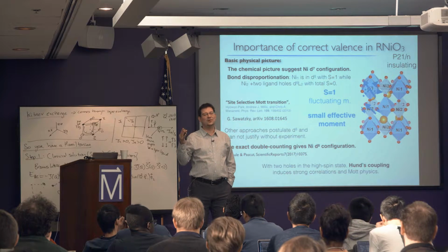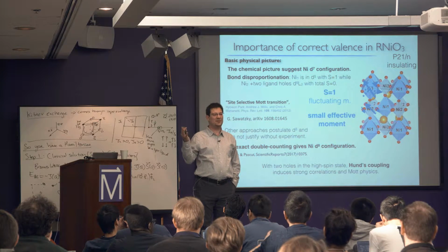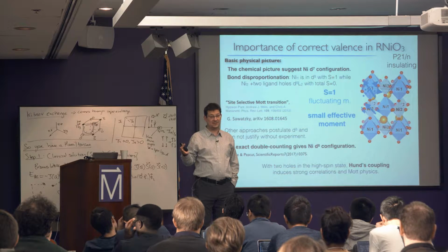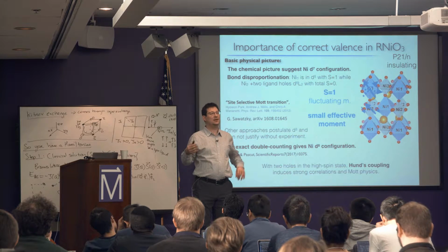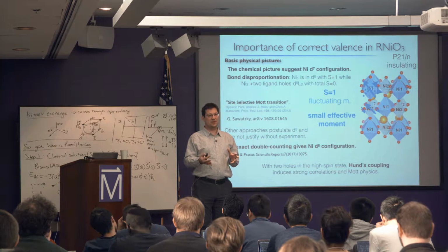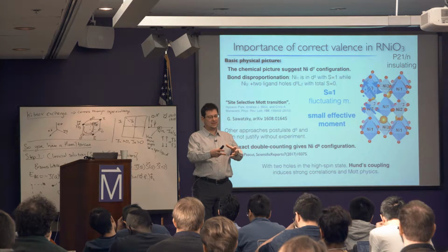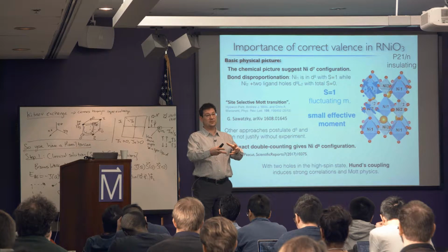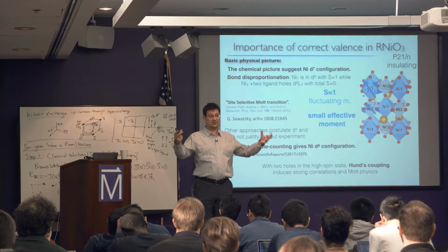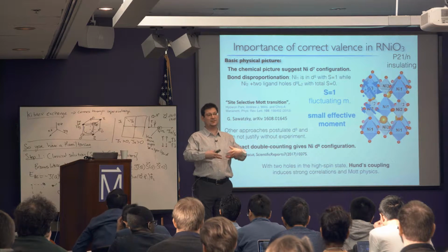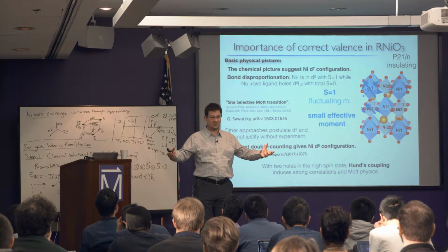There is also the question of what orbitals you pick. If you pick Wannier orbitals as your localized functions, you again typically get too large a valence. Why? Because in addition, your orbital then picks up not just the contribution of what we usually call D, but has a lot of oxygen content. So therefore, your valence is way bigger because it's not just D, it's also oxygen.